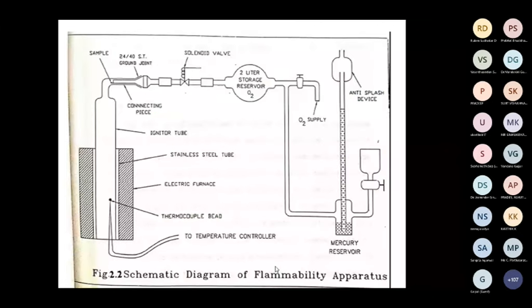So this is the instrument, flammability testing. This is the furnace. Here you take the sample, a finely ground sample. Here there is a solenoid valve. Here oxygen is in a cylinder under pressure. You go on increasing the temperature of the furnace as you decide. Once you decide the temperature, just open the solenoid valve. Through oxygen pressurization, the sample will be pushed through these tubes. There you watch the flame. If there is a visible flame, that is the ignition point. Otherwise, you increase the temperature by another 5 degrees. Going on, you increase the temperature, right from ambient or from 200 degrees where you start. At what temperature are you getting a stable flame? Each time you have to put the sample here, and then operate the solenoid valve.